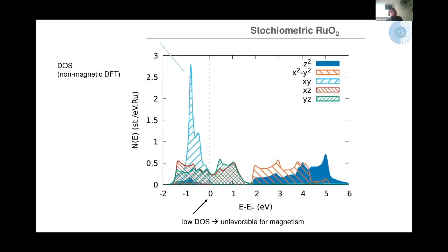And moreover, if we look at the density of states, which is also an indication of where we have the instabilities, when we look at the Fermi level, what we observe is that at the Fermi level, there is a strong depletion of density of states. So that means that you don't expect, in fact, an instability towards magnetism. But what is interesting about this density of states, which here is just shown orbitally resolved, is that one has a very large density of states in the occupied region, which of course could be reached, for instance, by doping. So if we put now some doping in ruthenium dioxide.